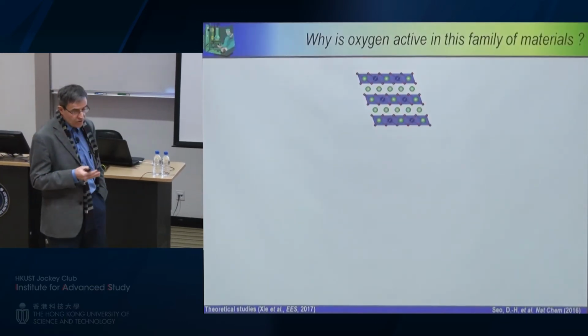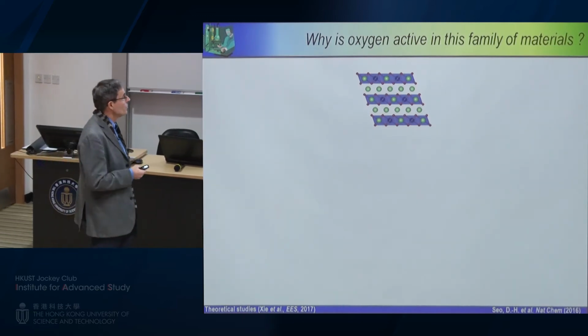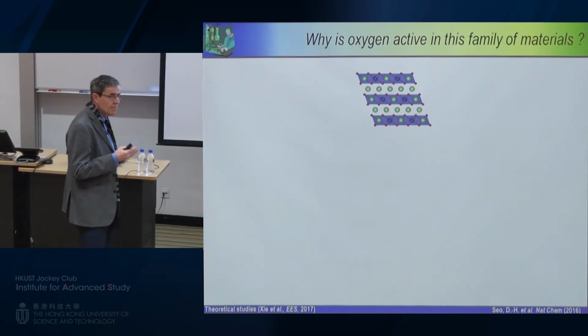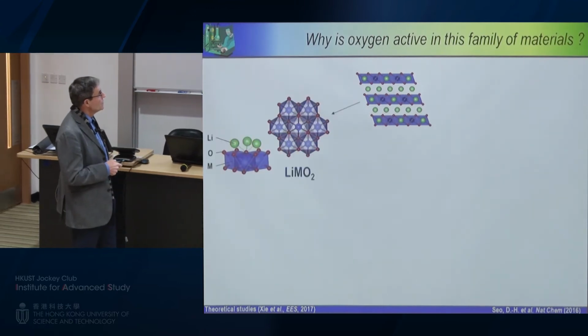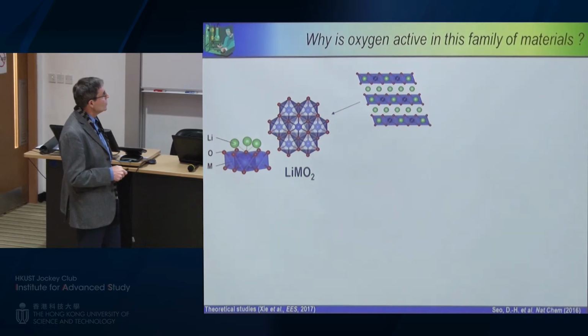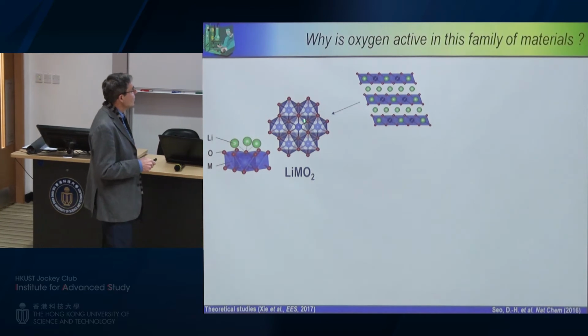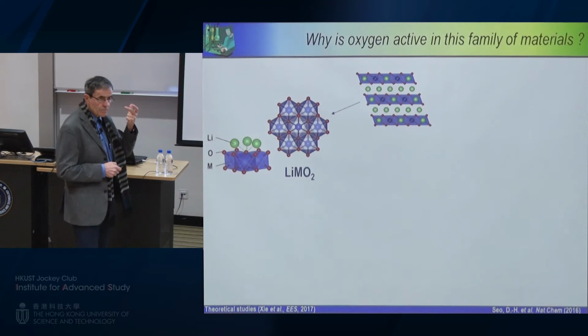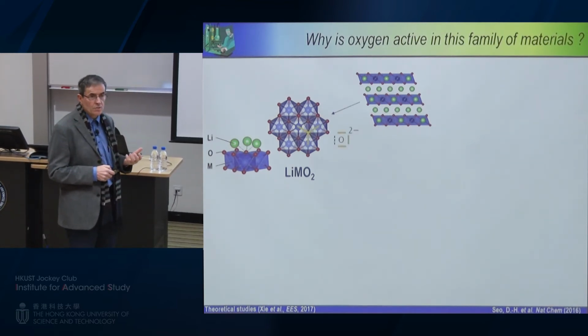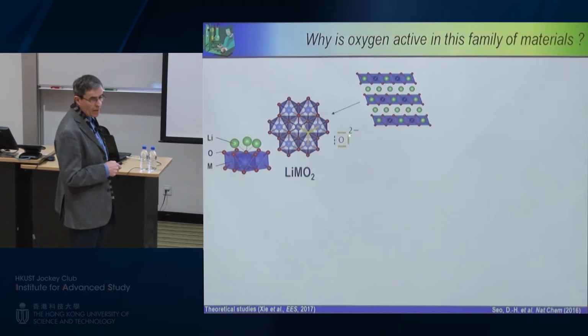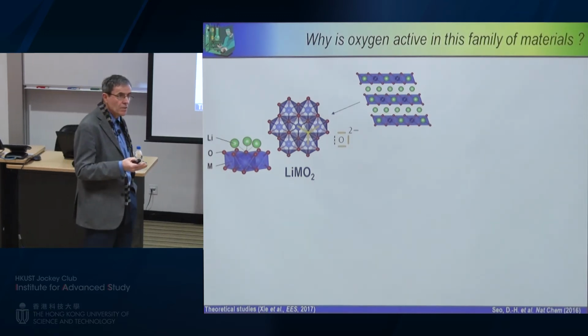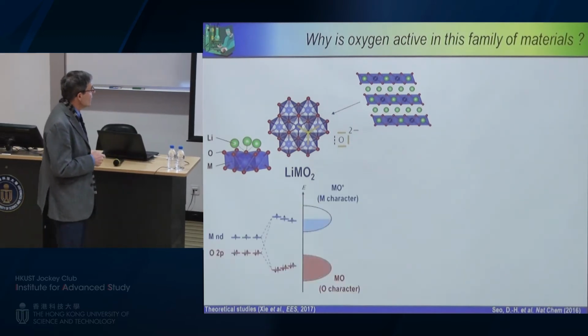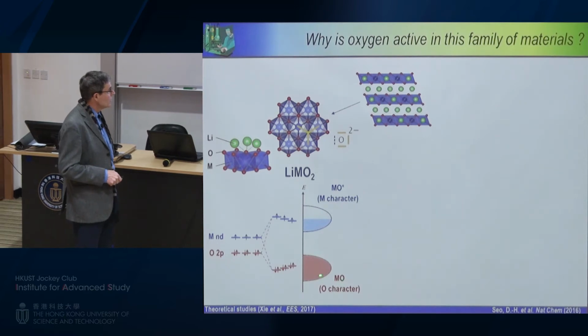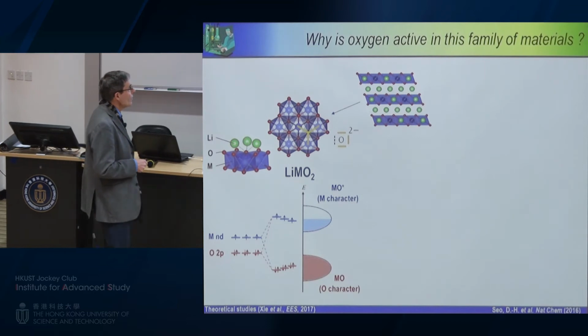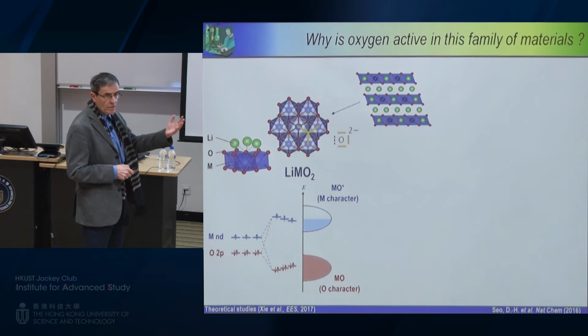Now, the question is, why is oxygen active in these materials? To convince you of why, I need to go back to the structure and explain it with very simple details. This is a layered compound that we have been dealing with, and this is more or less the structure of lithium cobalt oxide. You look here at the layers: in this case oxygen is red, and blue is the metal. Now we are going to consider the oxygen. All of you know that in the Lewis configuration, oxygen has three 2p doublets and one 2s doublet. Now you look at the structure: all the oxygen has its doublets participating in the bonding, which means that there is a nice overlap with the d metals. So in this case we get the classical band structure with molecular orbitals of bonding and non-bonding character. Now let's see what happens when I move from this LiMO2 to the lithium-rich compound, Li2MO3.